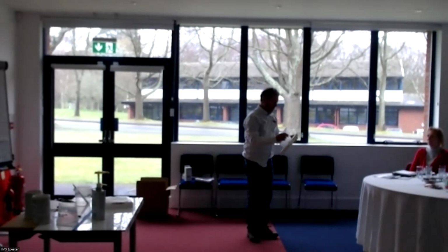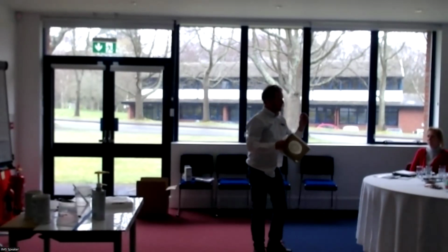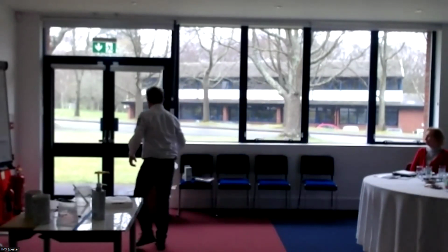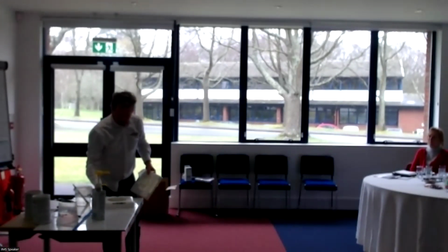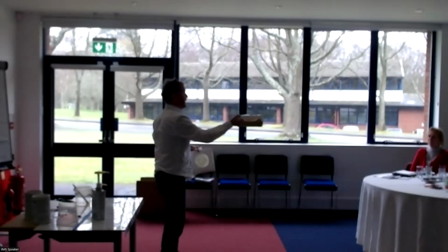There's another filler that we've got, which is more of the DIY type filler, but very valuable for the company. And you can see it on the edge here of this panel. It's very short chopped fibres of glass mixed with colloidal silica, which thicken the mix up. And you can stipple that in to a repair just on the edge of this, like a typical deck edge repair or typical corner of a rolled deck edge.